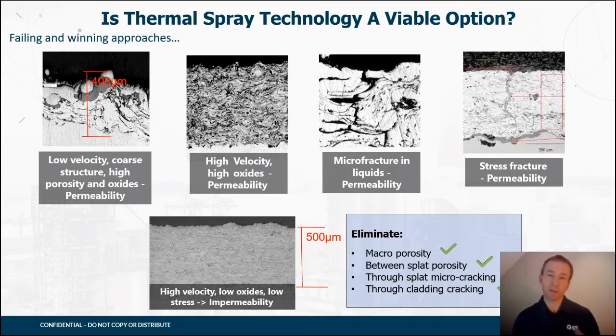Through that process and the development of conveyance systems for high velocity thermal spray, so we get the dense microstructure, and in alloy modifications, so we reduce the internal stress of the applied system, we eliminate the microcracking or the macrocracking, and we reduce the amount of oxides in that thermal spray layer. We're able to create an impermeable barrier to the operating environment that functions as a high nobility alloy on the surface to protect the underlying water wall tubes from metal wastage, from corrosion, but also from erosion.